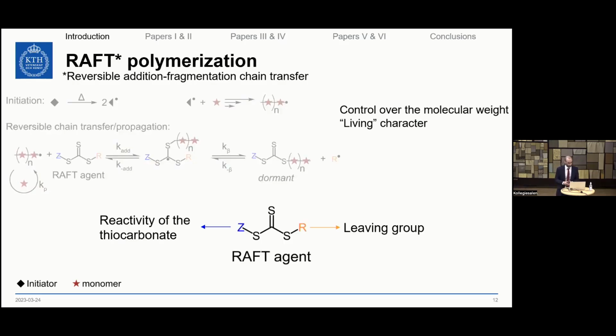This RAFT agent is comprised of two groups. We have the Z group, which provides the stability on the RAFT agent by controlling the reactivity of the thiocarbonate bond, and the R group, which is known as the leaving group. During RAFT polymerization, because of these rapid addition and fragmentation reactions, this R group leaves the RAFT agent, and it is responsible for further propagating the polymerization.